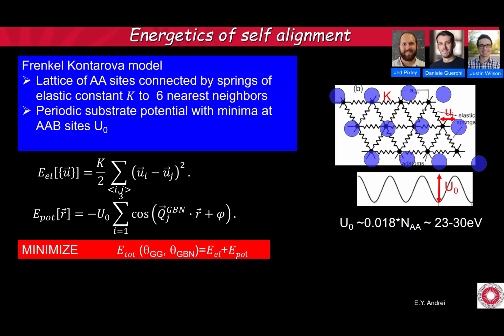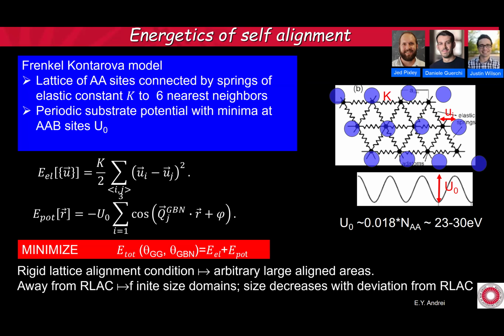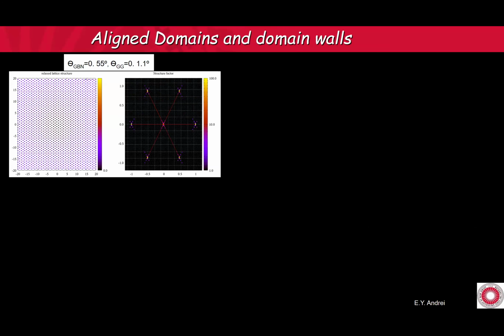So obviously, when you're perfectly aligned, there's no problem. You're going to get these huge domains. So if you are in the rigid alignment condition where the spring length is exactly equal to the distance between the minima, you're going to have absolutely no problem aligning your entire sample. But what happens when you're a little bit off, when you're just a little bit away from the rigid lattice alignment condition? And here is an example. So rigid lattice alignment, you see these nice Fourier peaks, the Bragg peaks.